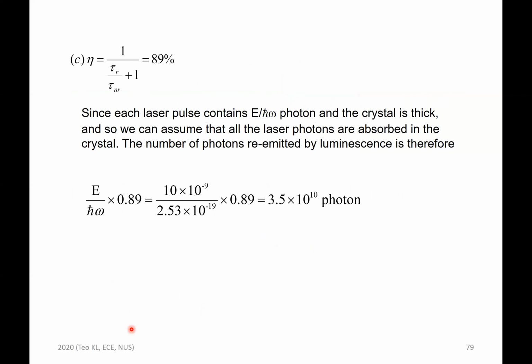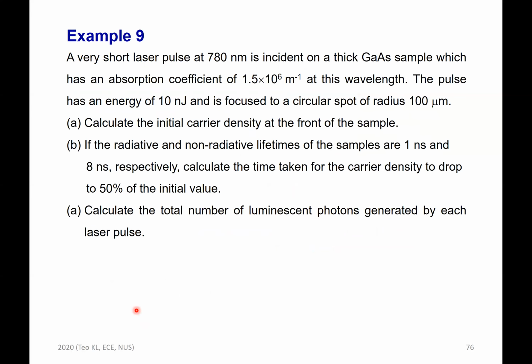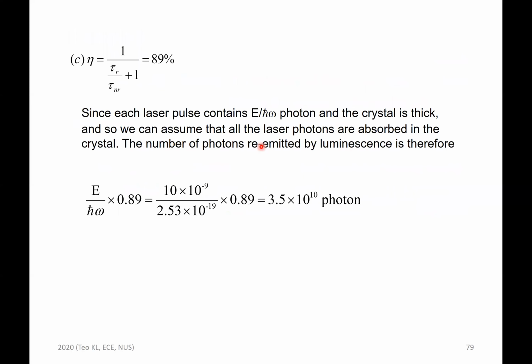Now, what is the efficiency? The total number of luminescence photons generated by each laser pulse. Remember, there's a non-radiative lifetime, which means there is a defect state or energy state, which is non-radiative, to capture your carrier. So the efficiency may not be 100% for radiation in semiconductors. So the efficiency will be 1 over tau r over tau nr plus 1, based on the previous equation. You plug in tau r, tau nr. So the radiative efficiency is 89%.